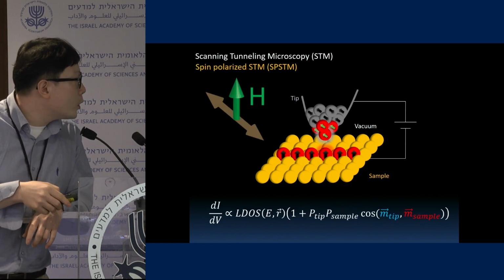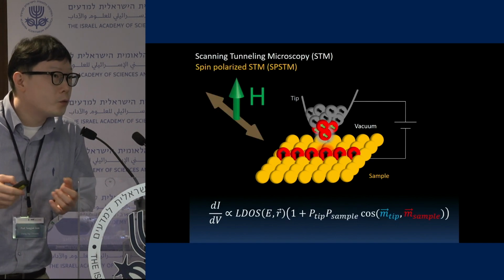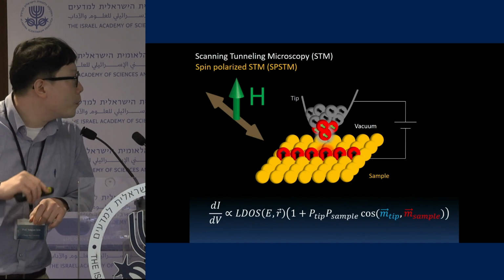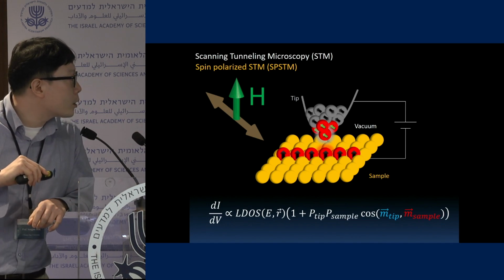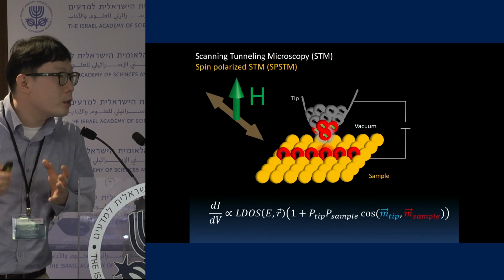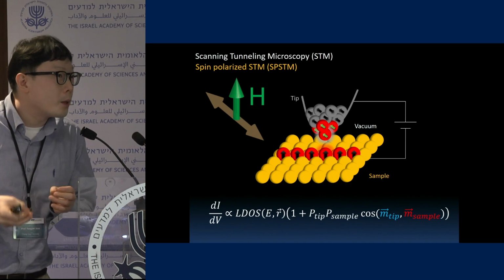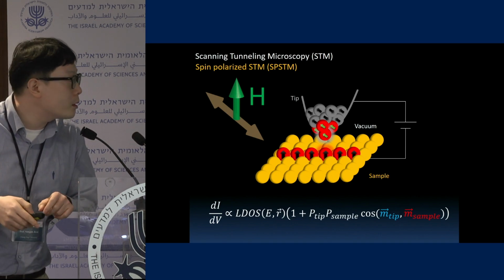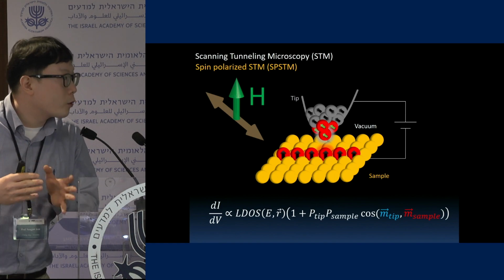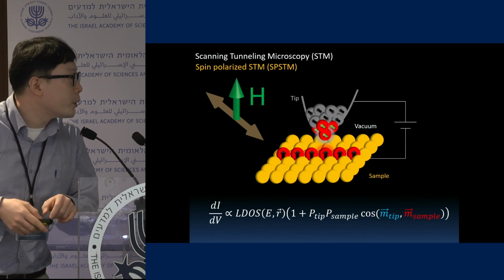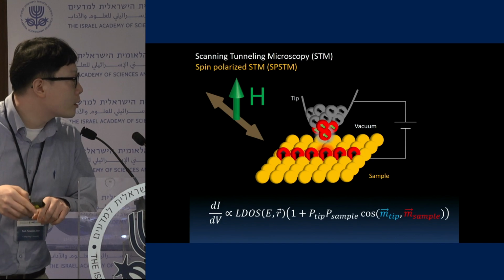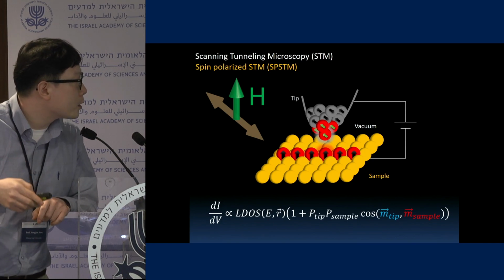And especially we use spin-polarized STM to further characterize the system. The tip is functionalized with some magnetic atoms, so the tunneling current has some spin component, and spin-dependent tunneling happens. So we can characterize what's really happening in this localized state. That was our measurement setup.